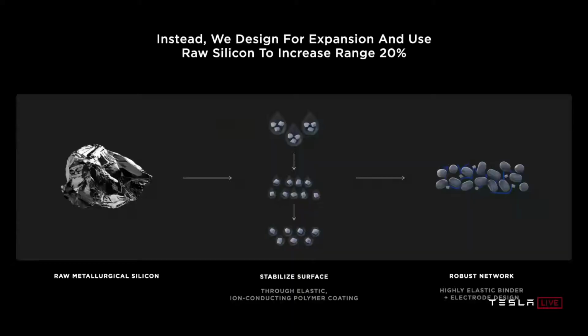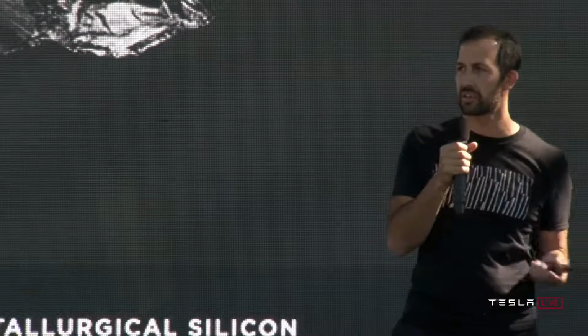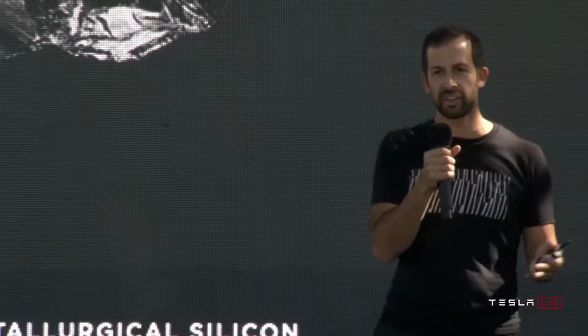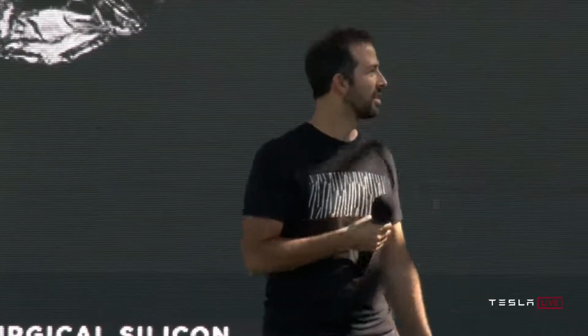And how does it work? Start with raw metallurgical silicon, stabilize the surface with an elastic ion-conducting polymer coating that is applied through a very scalable approach. No chemical vapor deposition, no highly engineered high-capex solutions. Then it's integrated into the electrode through a robust network formed out of a highly elastic binder. And in the end, by leveraging this silicon to its potential, we can increase the range of our vehicles by an additional 20%, just this improvement. Yeah, it gets cheaper and longer range.